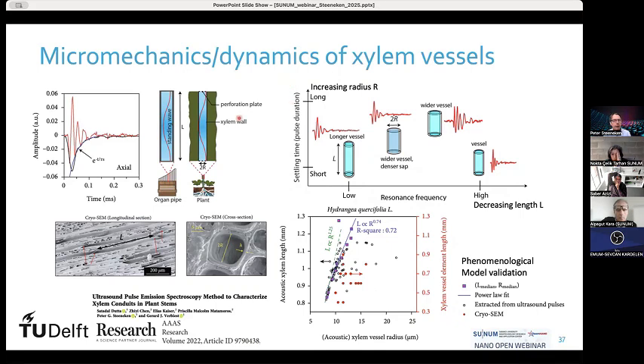We made a model which is a little bit similar to the model for an organ pipe. There are two types of frequencies. There's the standing wave, which, like in an organ pipe, depends strongly on the length of the vessel. So the resonance frequency here, if it's high, you are dealing with a short vessel, and if it's low, you're dealing with a longer vessel. But the radius of the vessel also has an influence on the shape of this decay. For large diameter vessels, we see a long settling time, whereas for a short radius, we're dealing with a short decay time.